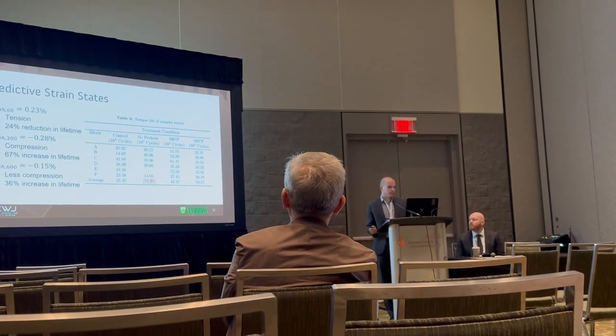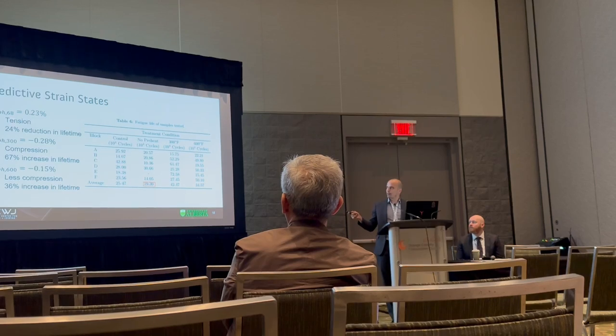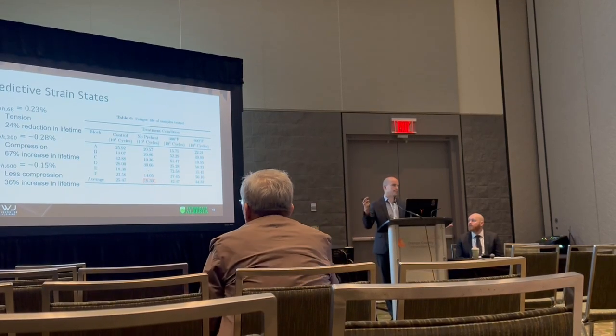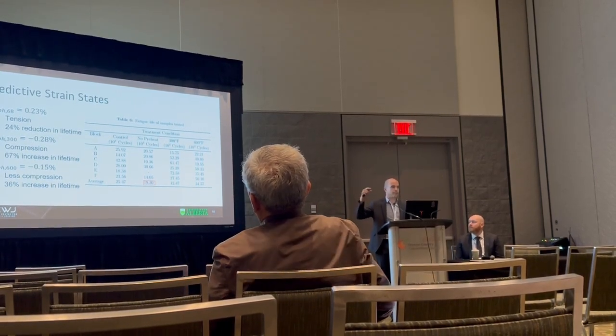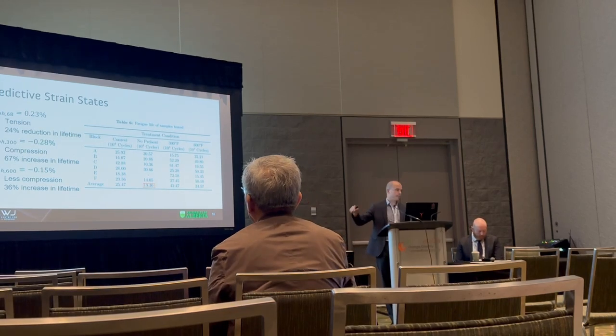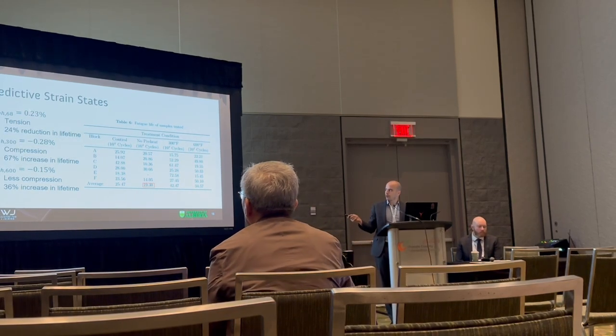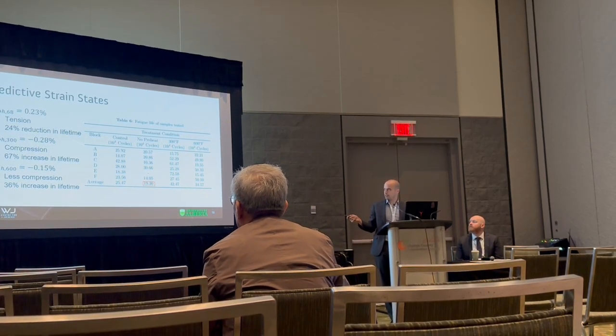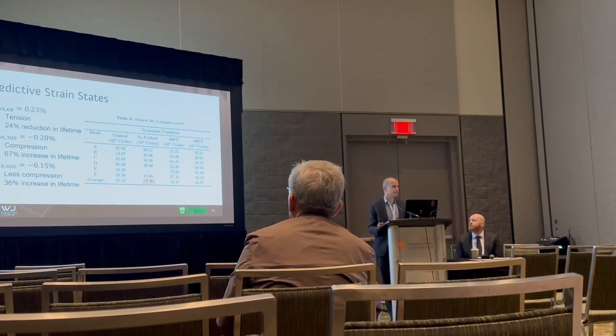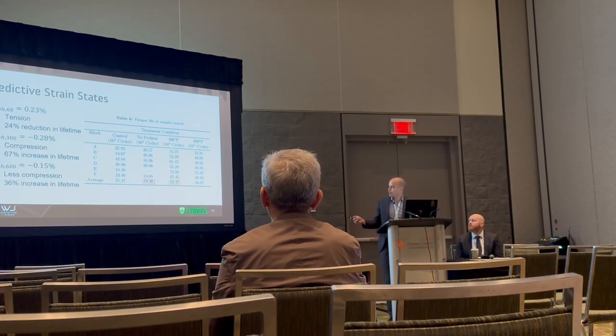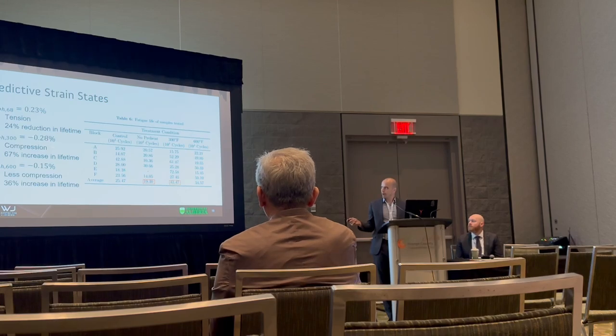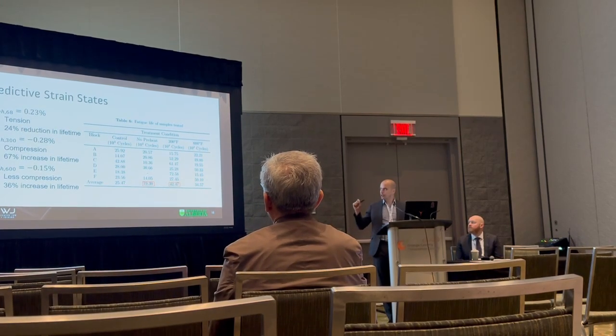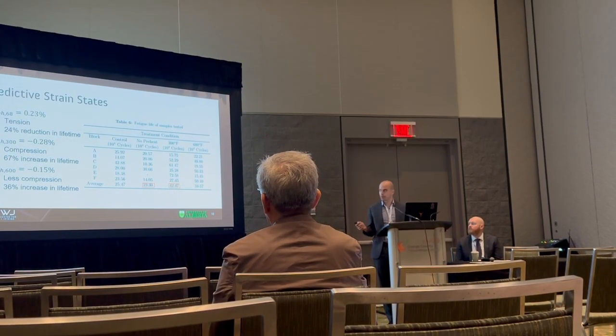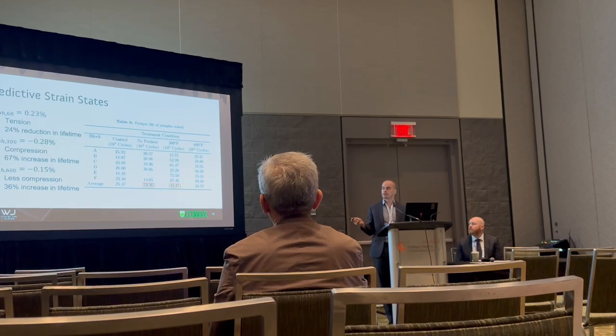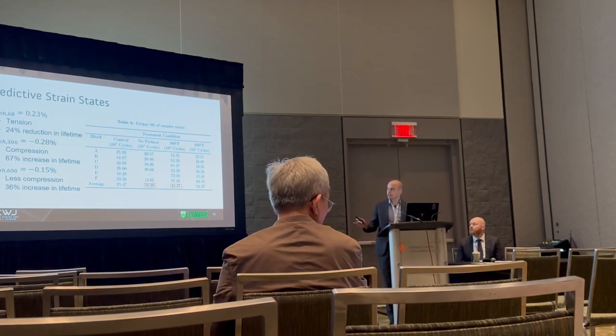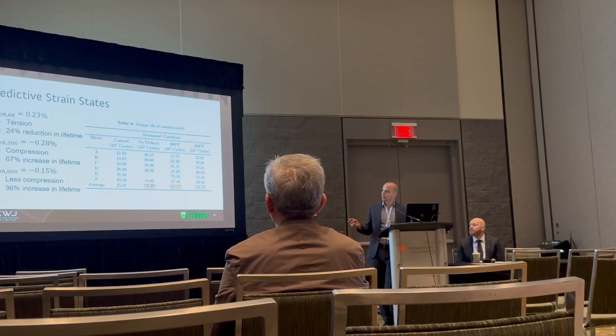So for our first one, I ran all the numbers to get what this actual strain would be. It's very easy to figure out, right? It's that epsilon phase over alpha is the slope of the curve, so then you can figure out the actual strain. So 0.23% strain, and look at this, a 24% reduction in fatigue life. So we look at the next one, the 300 degree case, we have a minus 0.28%, so that's 0.28% compressive strain, so we should see a pretty good improvement here. 67% increase in lifetime.